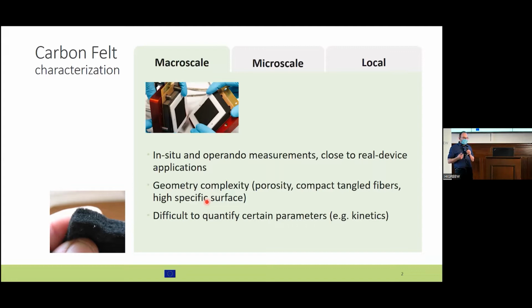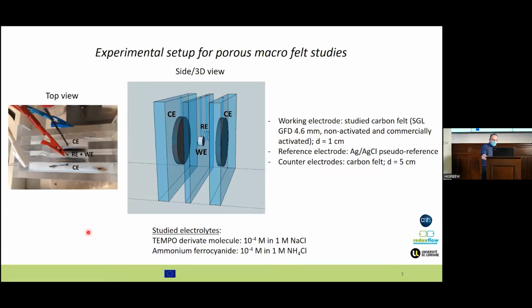The natural way of working is to start with the graphite felt. It's a porous electrode. We have here some representation. It is composed of fibers. This is a material we decided to use in HIGREEW. A priori, it is the best way to start measuring the electrochemical activity at this micro scale range. This is a typical cell we use, with a working electrode, and then a counter electrode in order to have a good distribution of current.